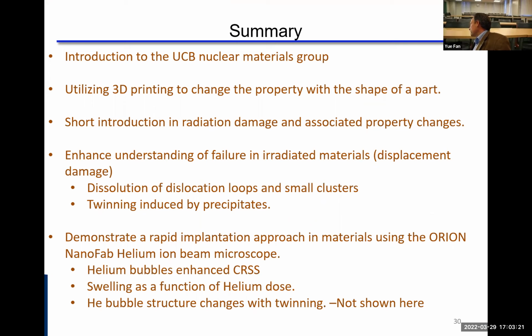We talked about 3D printing, changing properties along prints, either compositionally or microstructurally. Then we talked about displacement damage and what that means for a material without precipitates, like 316 stainless steel with its own loops and stacking fault tetrahedrons, or what that means for precipitate materials, that they can either dissolve or not dissolve and change deformation mechanisms. And subsequently, we talked about helium implantation using the helium ion beam microscope, and what that means for helium bubbles, that they change my mechanical properties. I didn't show the pillar version of this. It's the same as the other ones. If anybody really wants to see it, I can show you that too, but it shows the same thing.